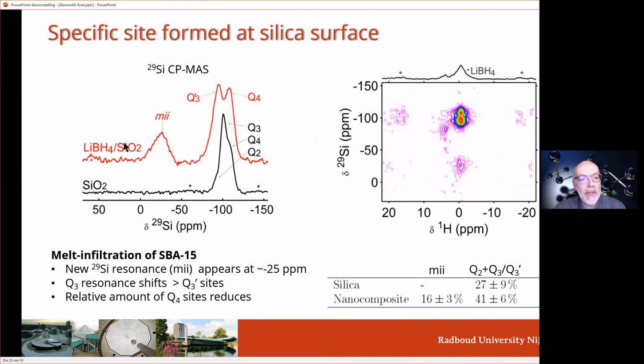And we started to look at the silica spectra. And the black spectrum here is the spectrum of regular silica. And we see 3 resonances, which essentially tell us about how condensed the SiO2 is. And there are OH groups at the center. We can do 2D NMR, where we correlate the silicon spectrum to the proton spectrum, etc. But it's very important that we find a completely new site.